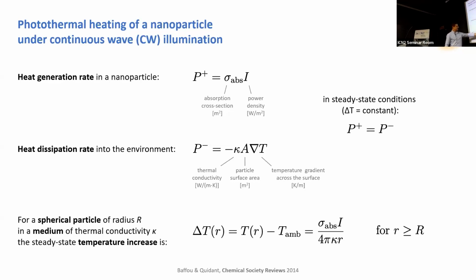And so if you take a spherical particle with a certain radius r, in a medium of thermal conductivity kappa, the steady state temperature increase, or delta T, which is the temperature outside of the particle, so at a distance r from the center, where r is equal or larger than the radius. So we are, let's say, plotting the temperature outside of the particle, minus the temperature of the ambient, that's the delta T. So it's a temperature increase with respect to the ambient, is given by the heat generation rate divided by 4 pi kappa r. And this is exactly the same equation that you see in the charged sphere, right? So how does it look like?